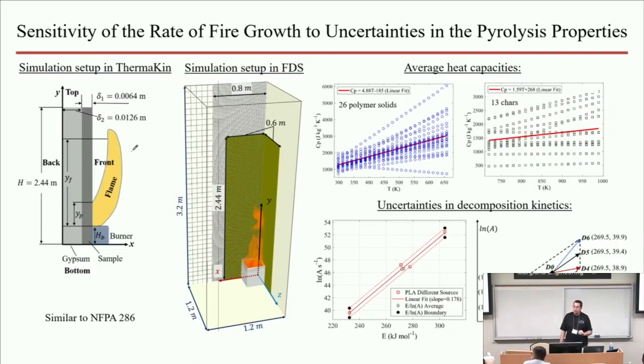But the interesting feature is that those properties are actually correlated, right? They're not really occupying that square. They only occupy this narrow strip right here, and that's associated with the so-called compensation effect. Compensation effect is something that people in the literature have argued about for decades as to where it comes from exactly, and I'm not going to add to that calamity.